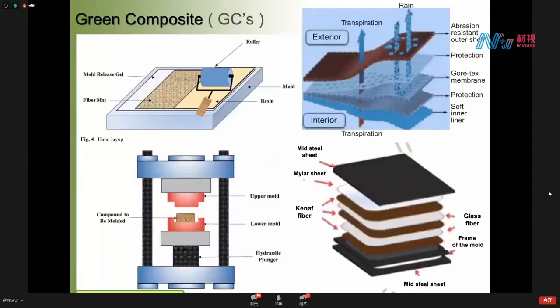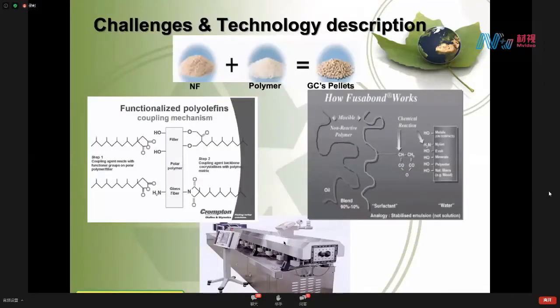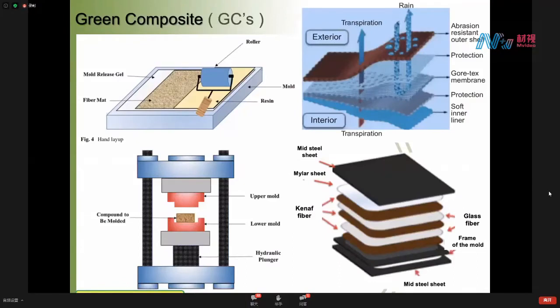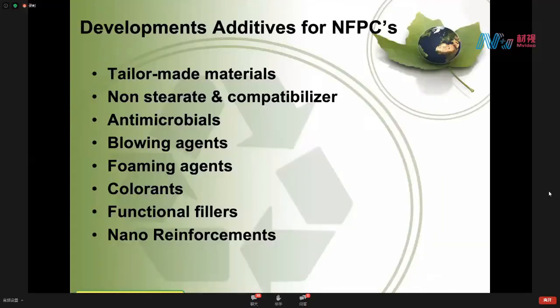For manufacturing of this green composite, we can use an extruder, a twin screw extruder, or we can also use press mold technology. Also, we can produce multi-layer or monolayer. Multi-layer can be homogeneous layers or heterogeneous layers. So we can use natural fiber together with glass fiber as layers submitted together in the mold, and we produce new materials. Also, we can use additives, such as stearates or compatibilizers, antimicrobial agents, blowing agents, foaming agents, colorants, functional fillers, and nano reinforcement.